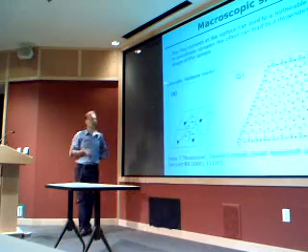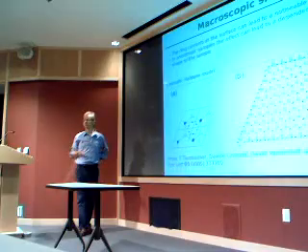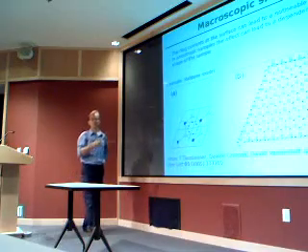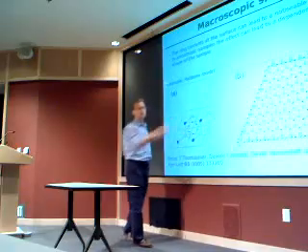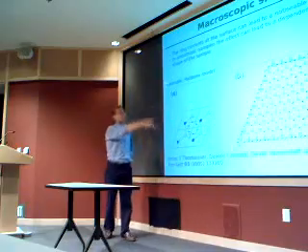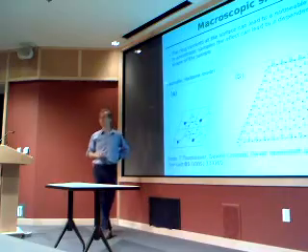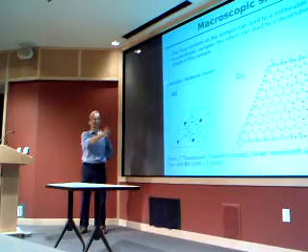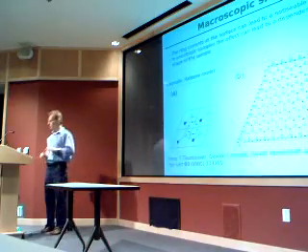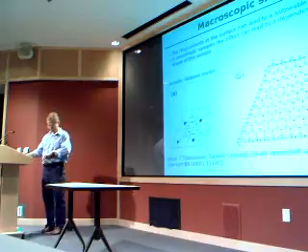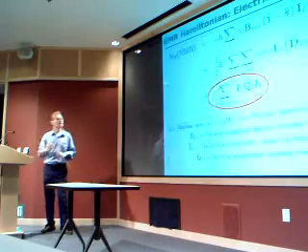Usually if one has big samples, like powder, it doesn't matter because you have all the orientations inside. But if it's a well-organized crystal, you get this surface current, and the output of the experiment depends on the shape. So it's important to keep in mind, and I will mention during the theory what one has to do about this.